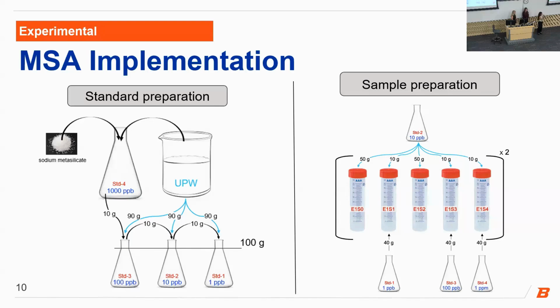And for sample preparation, we did some modifications to the standard MSA. We varied the concentration of the standards, but we kept the volume of them constant. And this will give us a plot that relates the instrument response with the concentration, and that will be a much easier way to calculate the concentration of the unknown.